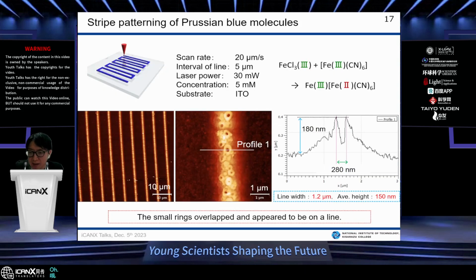So this is an experimental result. The setup is the same as the previous experiment setup. After bubble scanning, that means laser scanning, a stripe pattern was obtained. This is an AFM image, and AFM measurement revealed that the stripe pattern consists of an aggregation of nanorings.